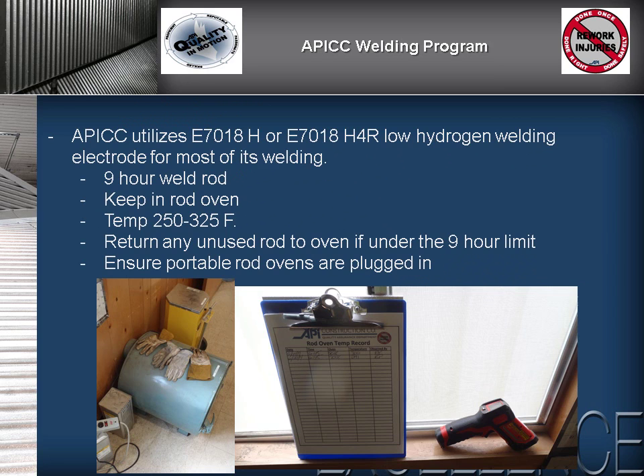Each weld electrode has its own specific storage and use requirements. Here at API, we primarily utilize an E7018H or E7018H4R low hydrogen electrode for most of our welding. This rod is usable out of the rod oven for up to 9 hours. Any rod outside the oven for longer than 9 hours needs to be destroyed properly. The rod can be returned to the oven provided it has done so under this time frame.